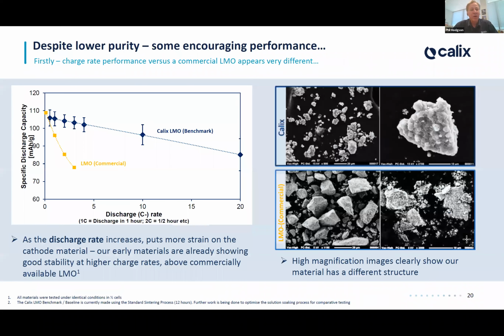Okay, despite lower purity, encouraging performance. Now, this LMO benchmark, you can see the error bars on it, so we've tested this many times. We're looking at this laid up against lithium manganese oxide cathode material in a half cell test. That's a commercial grade material. You can see the classic decline in performance that is typical of manganese oxide batteries. They're not very stable as you start to increase the discharge rate. And you can see our material here is very different.